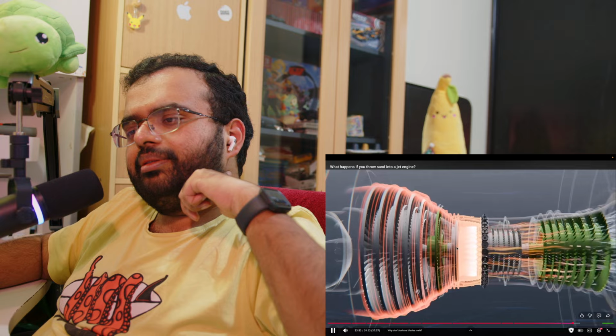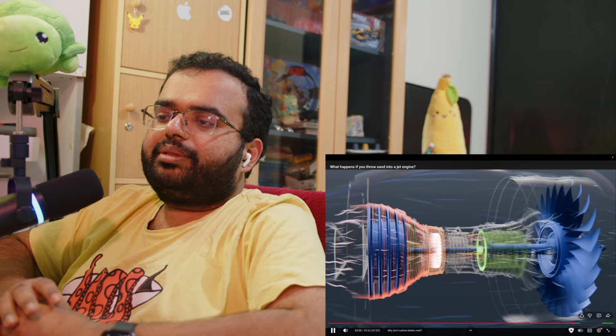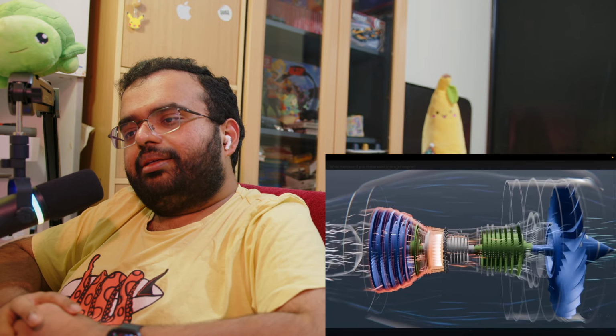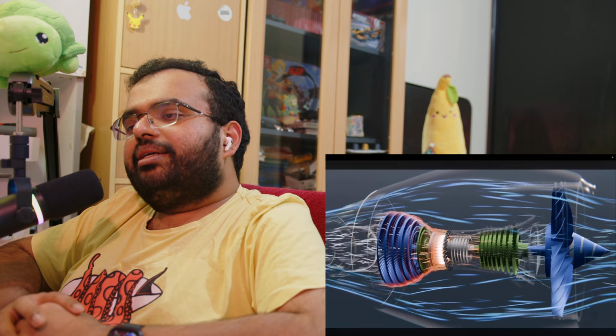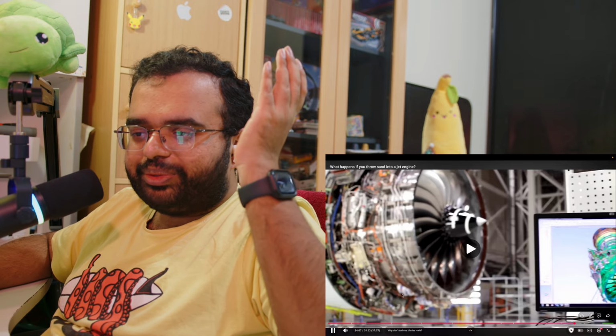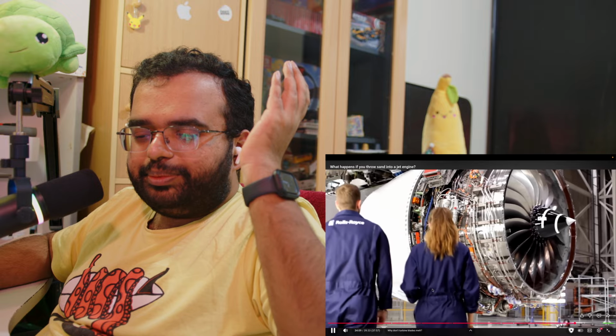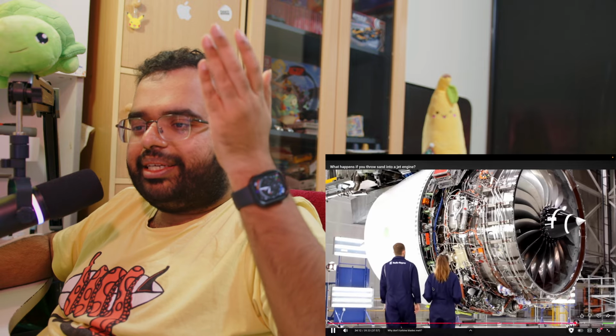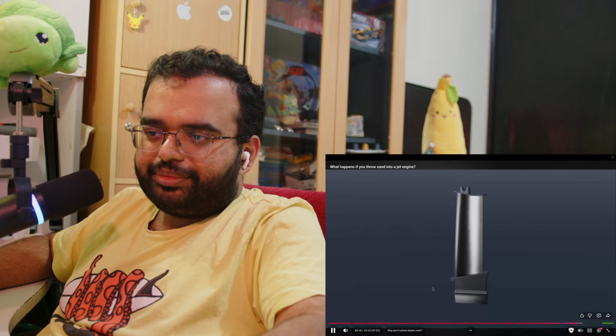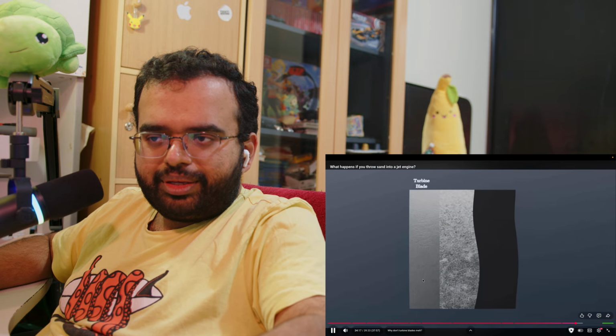This cooling air isn't exactly cold. It actually comes from the high pressure compressor section of the engine at around 600 degrees Celsius. But that is cool enough to help keep the blades from melting. But it's still not quite enough. And you can't just add more cooling air because... I imagine because if it's a bypass engine and you're putting a good 80% of your air through the bypass, you don't want to divert more of that bypass back into the engine, which reduces your thrust and efficiency, right? It's counterintuitive, right? So no. Because every extra bit of air you use from the compressor, you lose from thrust and actually make the engine less efficient. So every turbine blade is also coated with two protective layers.